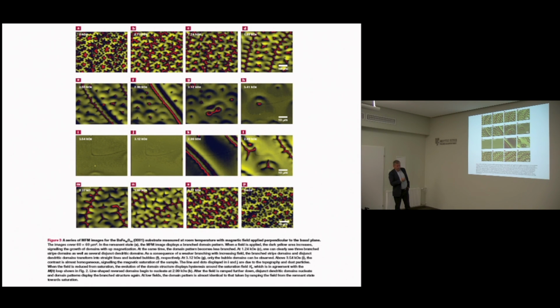Now, if the magnetic field is increasing, we have more yellow areas. It means that the positive domains grow, whereas at higher field, in some cases, the opposite domains have a shape like stripes. Then again, with the evolution at some magnetic fields close to the saturation, we have bubbles, and then around 3.4 there is saturation of the magnetization. Decreasing the magnetic field from saturation to zero is similar.